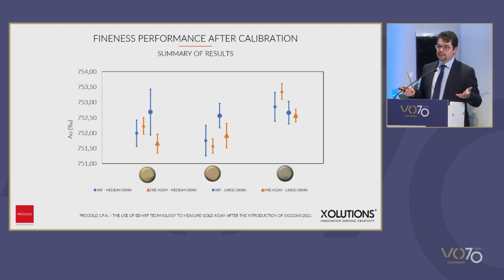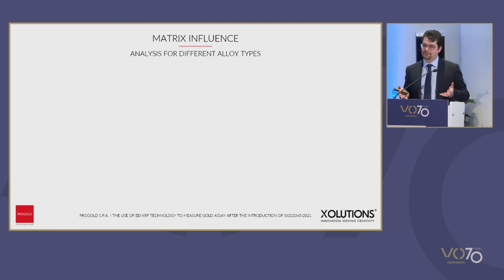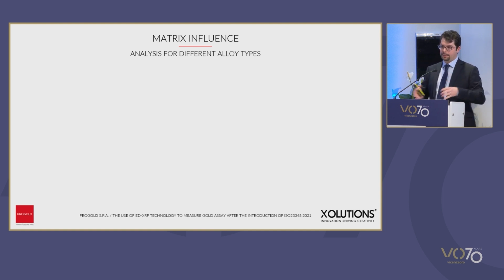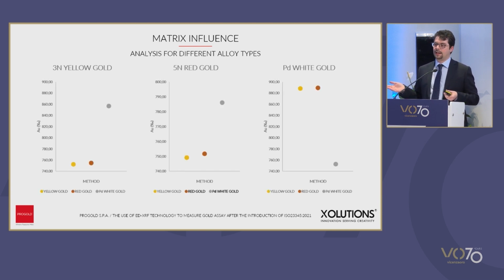Now, let's have a look at other parameters. What happens, for example, if instead of using a calibrated method for a specific composition, I want to measure the fineness of gold of another alloy? I'll make an example. And we crossed some data. We took the red gold and we used the same method that we had used for the yellow gold, in order to measure the importance and the influence of matrix.